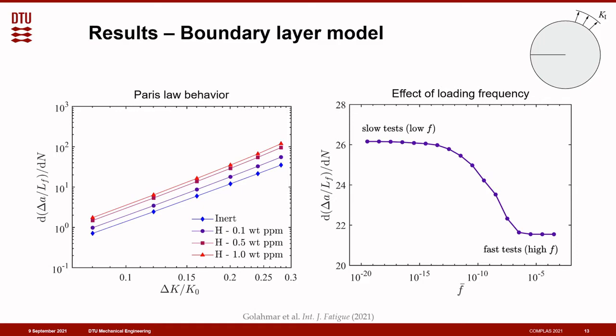In addition, as you can see in the right figure, the model also captures another widely observed experimental trend. So what we have here is the speed of the fatigue crack growth as a function of the normalized frequency. In general, the fatigue behavior of metals in the presence of hydrogen varies between two limiting cases, as I'm showing in this figure. First, we have fast test or high loading frequency, where hydrogen does not have enough time to diffuse to the fracture process zone, and therefore the susceptibility to embrittlement reduces.